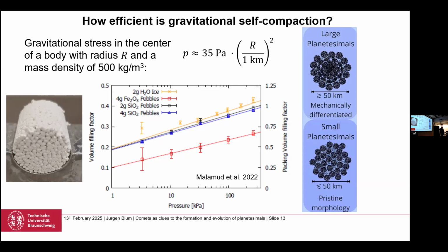So we did experiments. We formed pebble piles, we compressed them, and looked at what happens with the porosity. So a measure for porosity is the volume filling factor. So this is the fraction of the overall volume really filled with material. So we start at about 20% filling factor, and as pressure increases, so as the bodies grow bigger and bigger, or as bigger and bigger bodies are considered, they compactify. And that has influence on the thermal conductivity, on the tensile strength, and many, many physical properties in the inside of those planetesimals.